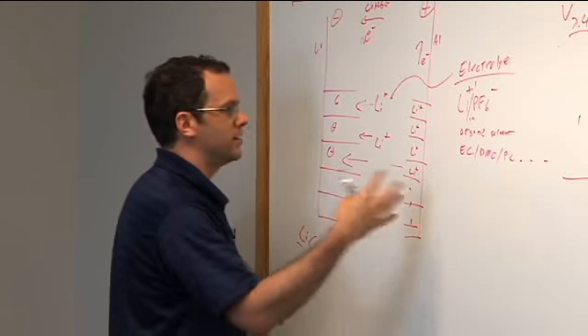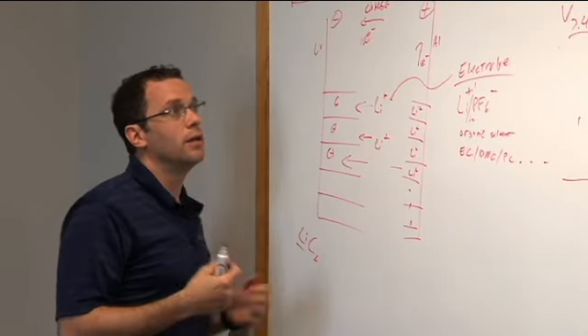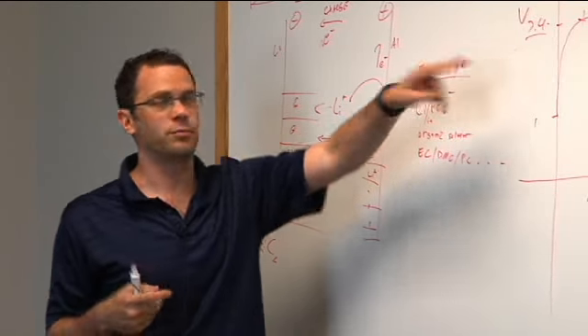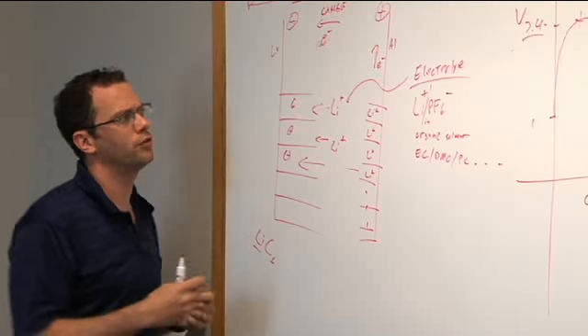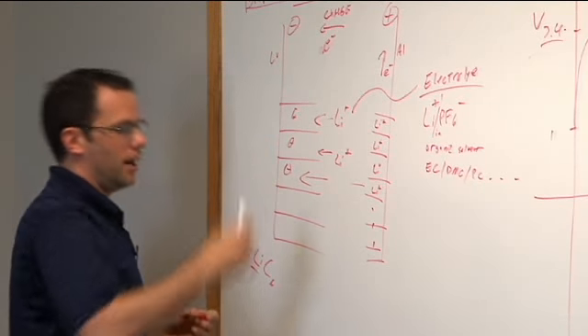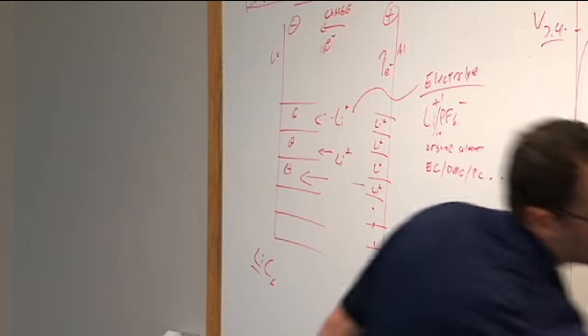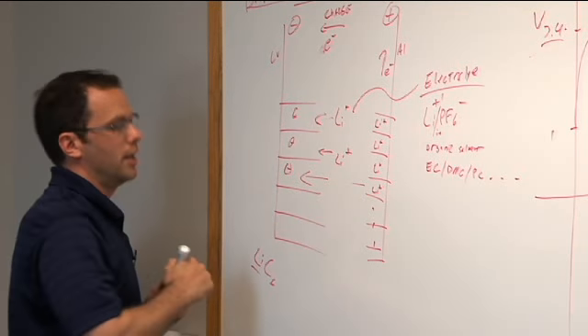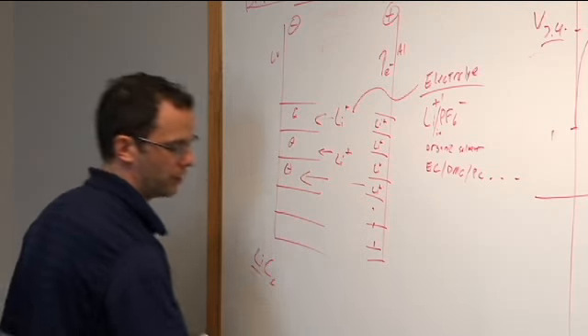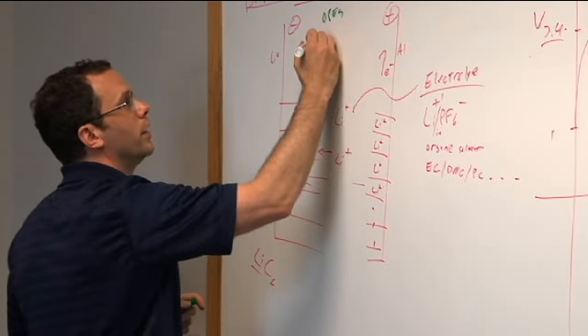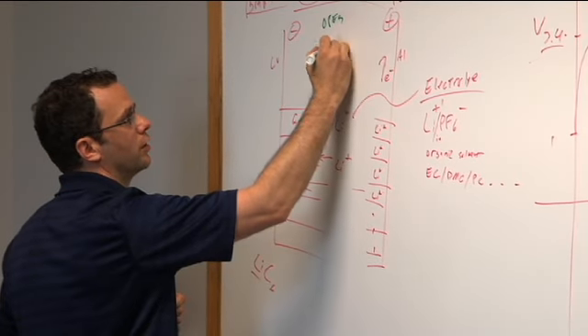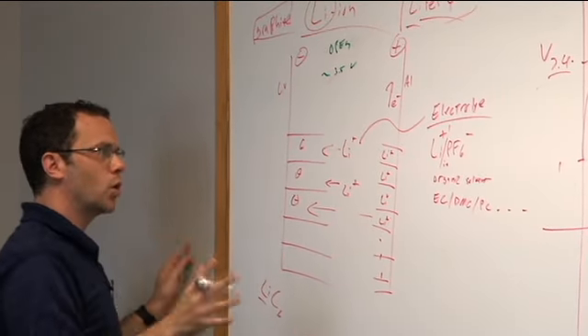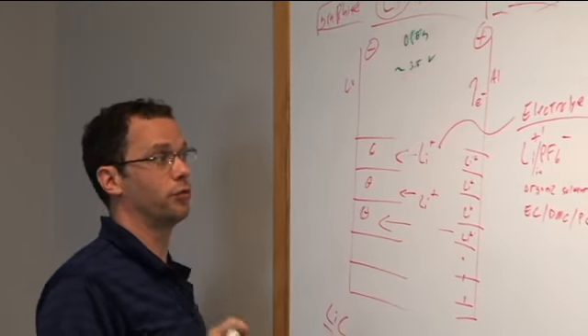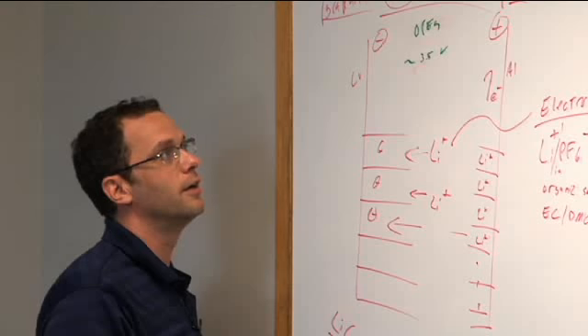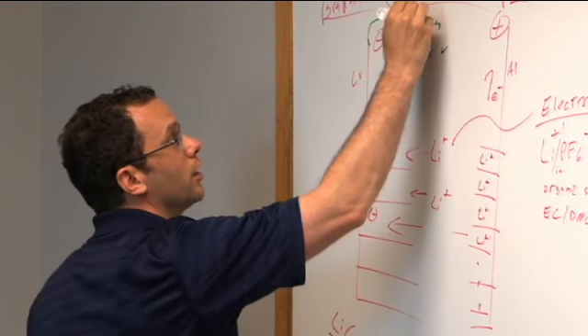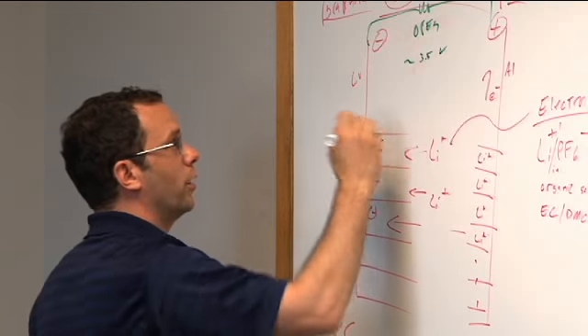And so how badly does this lithium want to go back into the lithium iron phosphate? Its driving force is 3.4 electron volts, right? That's how badly it wants to go. And 3.4 volts is quite a bit. It really does want to go back. So if we stop charging it, if we take our power supply off and leave it open circuit, we have an open circuit voltage of something like 3.5 volts if we're fully charged, right? And no current can flow. Because no current can flow, even though there's 3.4 volts worth of energy, these lithiums want to go back here, they can't, okay? Now, if we then supply a load, we allow electrons to go this way, right?